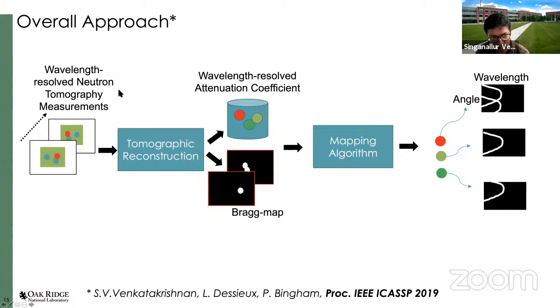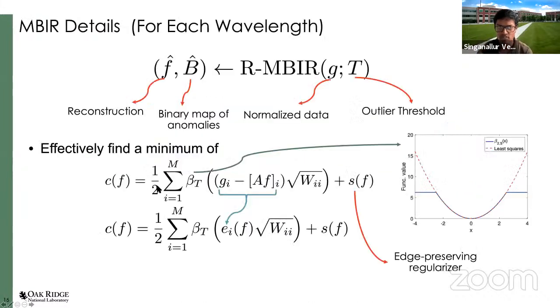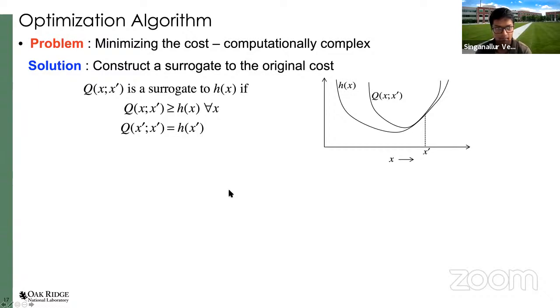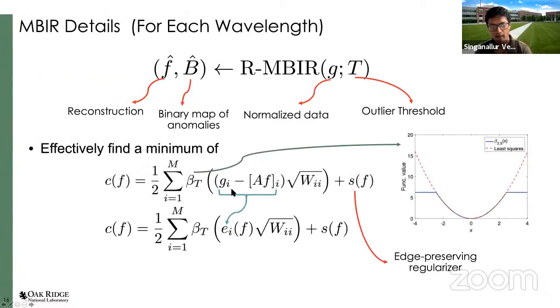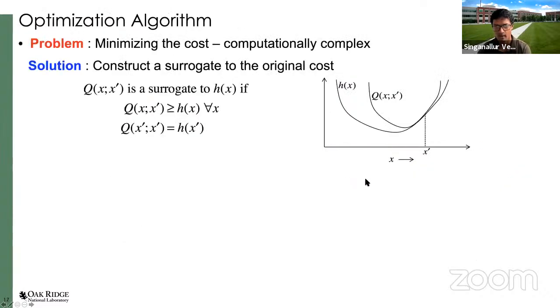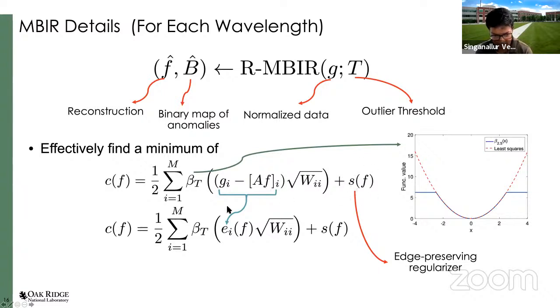So how do you do a tomographic reconstruction from such data, right? Because it's diffracting very strongly, and you have this transmission data. The key piece of doing the tomographic reconstruction is to use what we call a robust model-based iterative image reconstruction approach. In this case, you can imagine we're doing reconstruction for a single wavelength for now. The whole idea is that we formulate the cost function, and the first term is based on a Huber-like penalty applied to the projection, right? So you have the forward operator on the 3D object at a certain wavelength, and this is a weighting function, which in transmission tomography is typically set to the counts itself. And for the regularization, we use a standard regularizer.